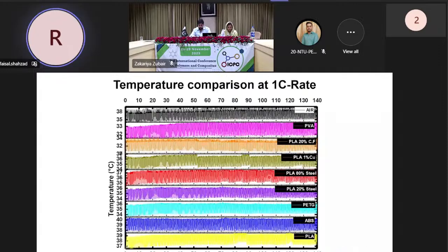Then we have tested our material at 1C charge and discharge rate of the battery. It's almost 140 hours, we continuously charge and discharge the battery for more than 140 hours.